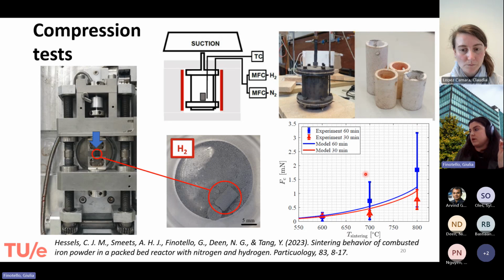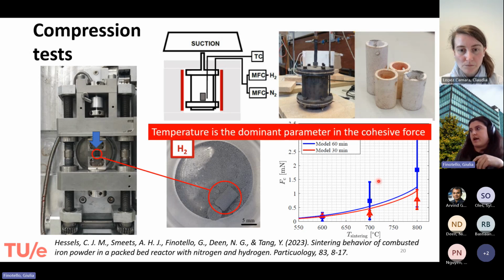And we found that the time of sintering, if we performed the experiment for 30 or 60 minutes, didn't have really a large effect. The temperature has a dominant effect, which is something that is really critical. The temperature, indeed, for this problem, is very critical.